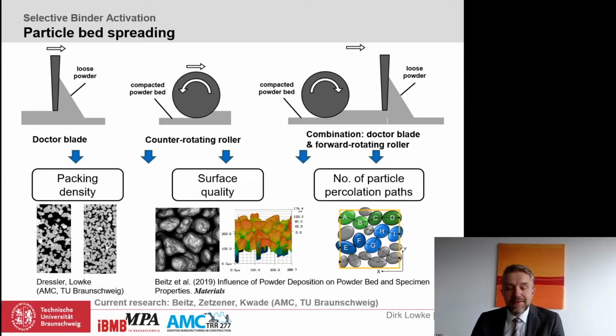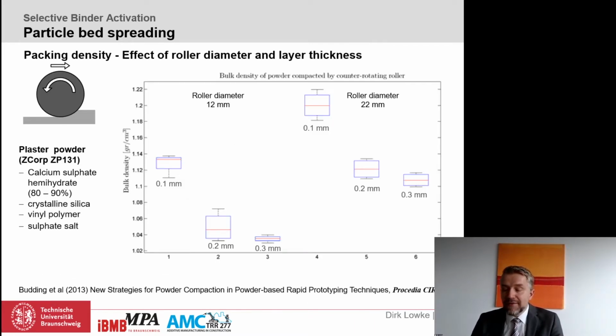Thus, to increase the density and the strength, we have to increase the packing density of the particle bed, as well as the number of percolation paths. One way to achieve this goal is to adjust the layer thickness or the roller diameter. As you can see here in this diagram, the density, for instance, decreases with increasing layer thickness, but increases with increasing roller diameter. I believe that increasing the packing density of the particle bed is the key to increasing the density and the strength of our components. Therefore, the focus of future research should be particularly placed on a specific compaction process of the particle bed.